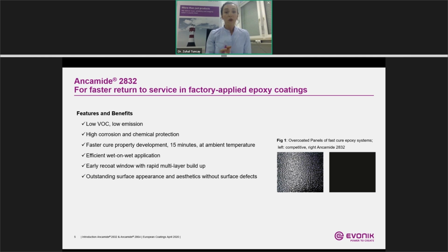Then you see the result for the competitive curing agent on the left side, with a very poor surface appearance. Compared to this, on the right side is 2832, used as primer and top coated after 15 minutes. Here we could achieve a very good aesthetic for the surface without any defects.